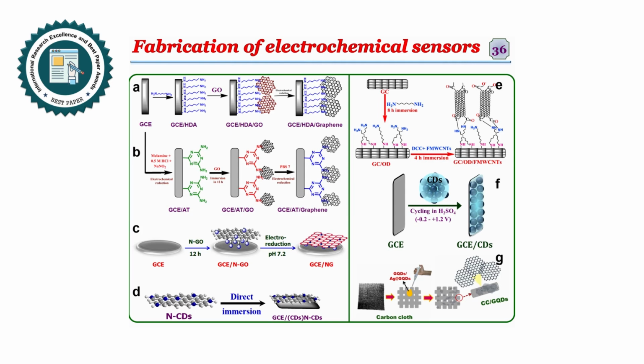So the third part is the direct immersion. The amine group from the nitrogen-rich carbon material is utilized for effective attachment via the direct immersion technique, with the help of a coupling agent, DCC, and with the potentiodynamic method and the drop cast method. These are all the methods utilized for the fabrication of electrodes.